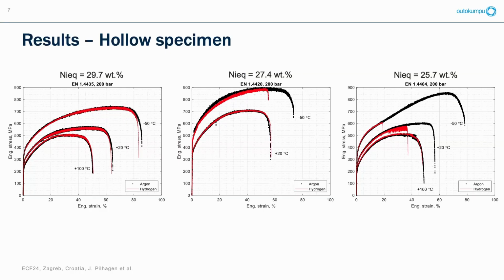So here we see some engineering stress strain curves for the 3 different grades. For the 4435 with the highest nickel equivalent, it doesn't seem to be degraded by the hydrogen. You have some martensite formation in the necking region at -50. And for the 4420, you have no embrittlement at room temperature, but it fails around the necking region at -50.